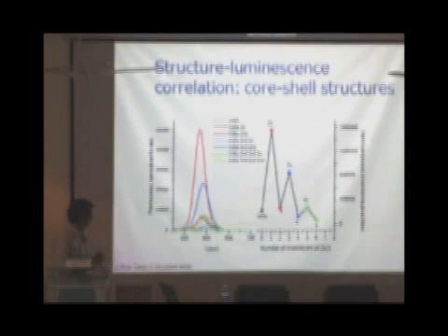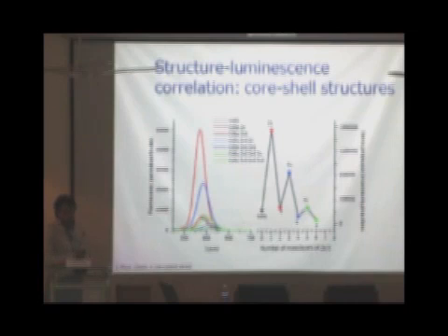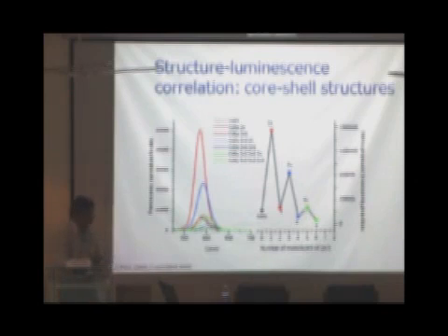So this is a cadmium selenide core coated with a zinc sulfide shell. The very interesting thing was that it really depends on the kind of surface atoms that you have. Surface plays such an important role. So if I coat one monolayer of zinc, okay, the fluorescence intensity shoots up. But then if I coat a second monolayer of sulfur on top, intensity comes down. So zinc is very crucial. Although the coating is zinc sulfide, and the type 1 structure that we are forming is because of zinc sulfide, the sulfur on the surface brings it down.